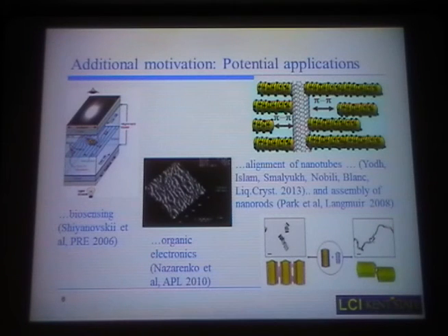You haven't tried amphiphiles or anything like that? No, what we did here to switch from one behavior to another is that the functionalization of the gold particles is different. In one case, you have the sides that are more electrically negative, and in another case, you have the top and bottom that is more electrically negative, and that directs the chromonic aggregates to either the top and bottom or to the sides, and that's how the change in geometry occurs.